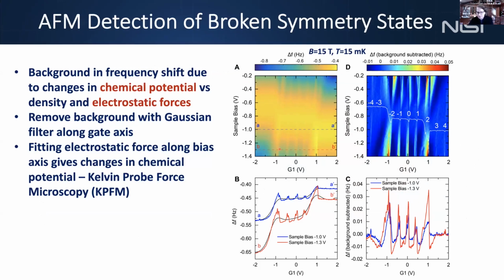And you can see that a little more clearly if I just subtract a smooth background here, get rid of this background, which I'll talk about later. That's the chemical potential. And you can see the broken symmetry states have a frequency shift here in the bottom of about 20 to 30 millihertz. And if we subtract that background here, we can just replot this data.